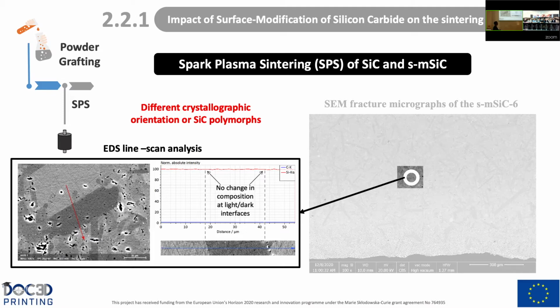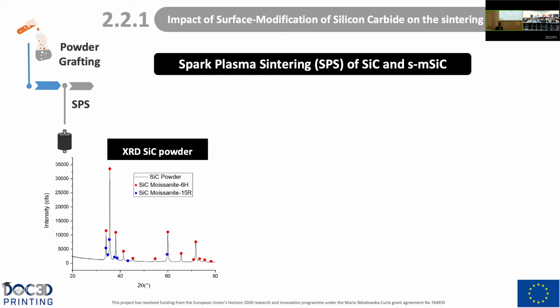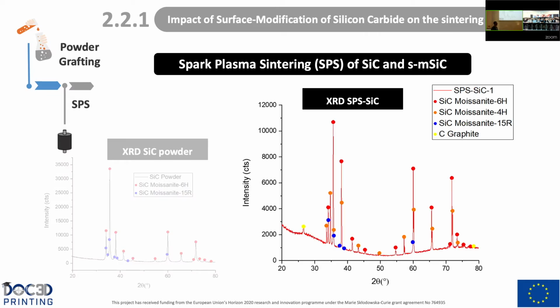So actually what we have here are different crystallographic orientations of different silicon carbide polytypes. Now regarding the XRD spectrum to know the phases of this material, here again the powder as received. If we compare with the silicon carbide after spark plasma sintering, we can observe moissanite 6H, 15R raw material, like the powder, and some graphite due to contamination of the graphite die that we are placing in the beginning. But actually here we observe a new phase, silicon carbide 4H, that is not present in the powder.